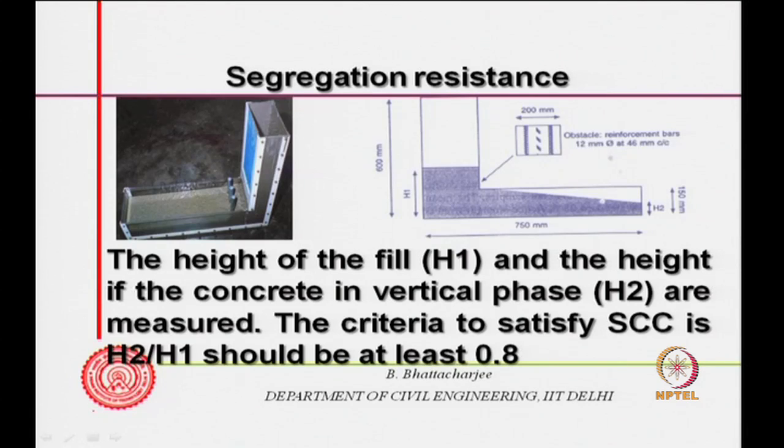So, it should be at least 0.8. It should satisfy the criteria: to satisfy SCC, h2 by h1 should be at least 0.8. If it is 1, that is very good. So, that is what it is.